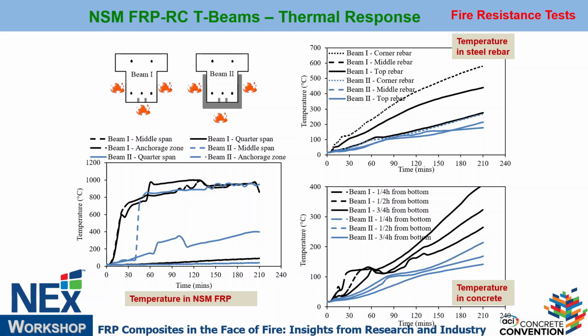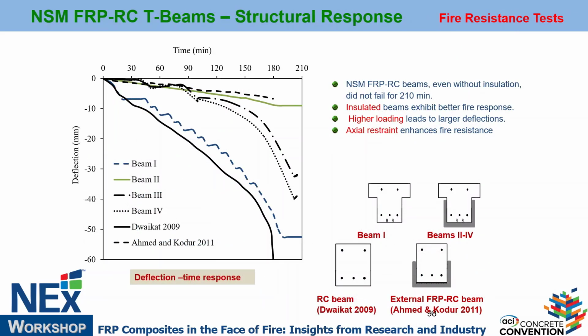In FRP itself, you know that NSM FRP slots, as you can see, if you don't insulate, the temperature quickly rises. They don't have anything to contribute after 15-20 minutes into the fire. Right? So then same thing, deflections. This is externally bonded. This is a conventional reinforced concrete beam. When you strengthen it with outside FRP like this with insulation, this is how it behaves. This is the deflection in the beam. And these are NSM. So NSM is possible to get required fire resistance without any insulation up to 2 hours.